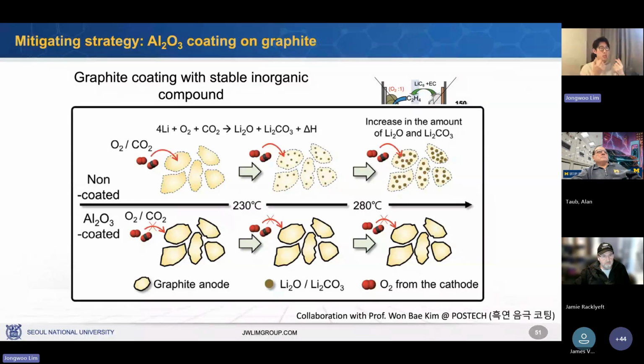Now, what we found interestingly, very thin aluminum oxide is not impeding lithium transport significantly. However, it helps form favorable SEIs. It's even better in the cycling performance in the very early cycles. That's a very interesting phenomenon we found, and we don't know the reason. The capacity actually does not get better, interestingly. Yeah, we found the same thing, but also struggling with the explanation. Thank you.